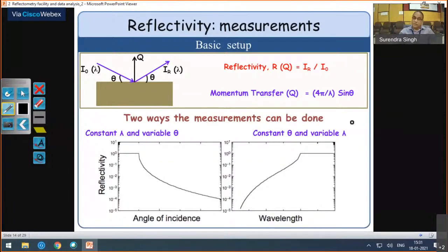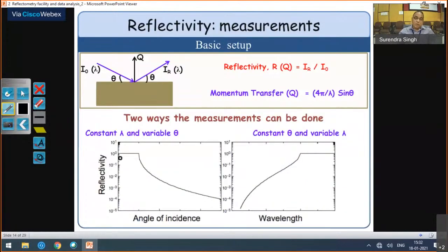It doesn't matter whether it is variable lambda or variable theta. One case, with a constant lambda, typically happens at a reactor source, where we have a continuous source of neutrons, and we take one particular wavelength and change the angle of incidence to do the reflectivity measurement. The other case, with variable lambda, is typically adopted in pulsed sources like synchrotron or spallation source based neutron reflectivity.